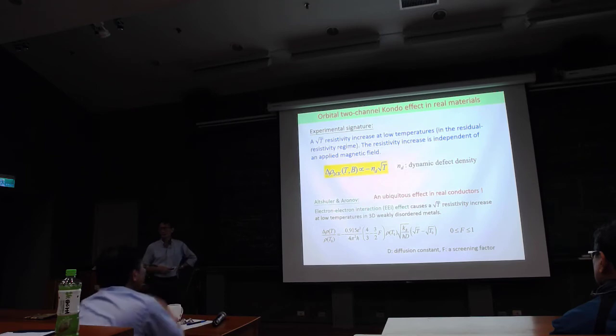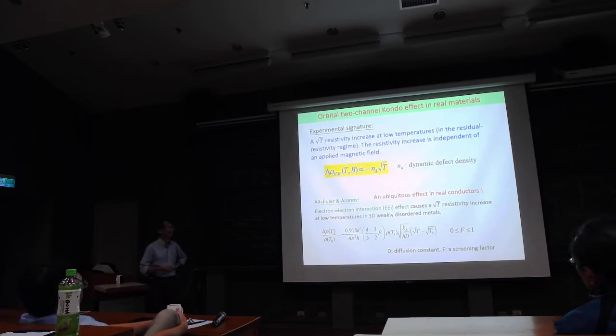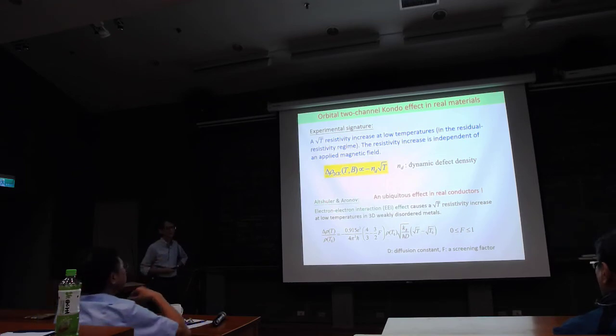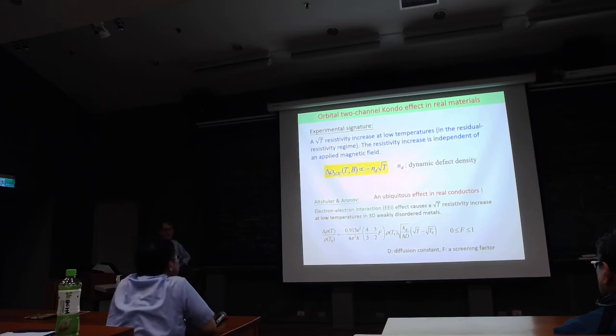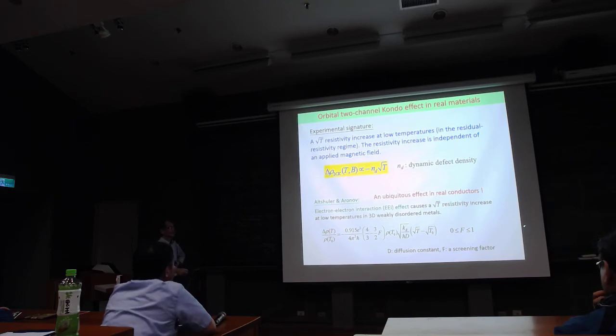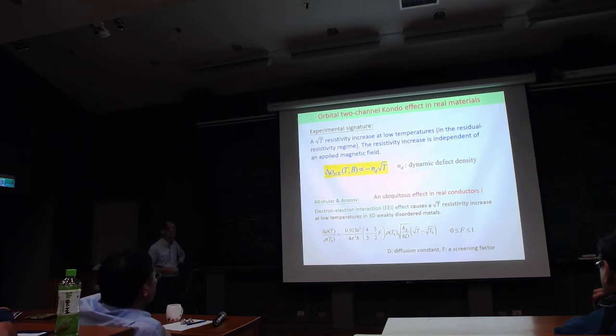when we work on real conductors, metals, or heavily doped semiconductors, we know real materials are always disordered or weakly disordered, always contain defects, even a small amount of defects. And in the late 1980s, or in 1980, people also realized, Altshuler, Aronov, and partially Lee also made a very great contribution to this effect. They realized that in real materials, it is usually weakly disordered. That means we have defects. And if we have defects, then the density of states will be modified. And as a result of this slightly suppressed density of states, a real metal always gives you at low temperatures a square root resistivity increase at low temperature.